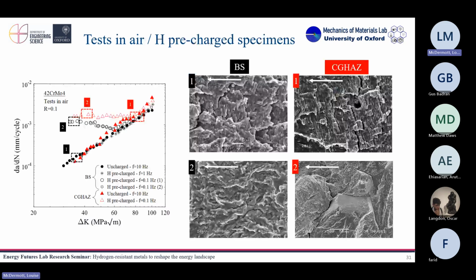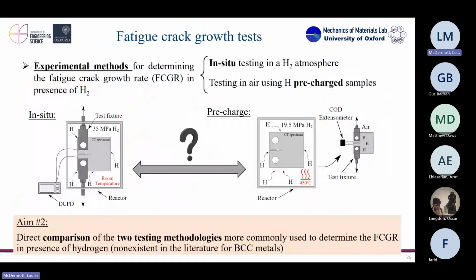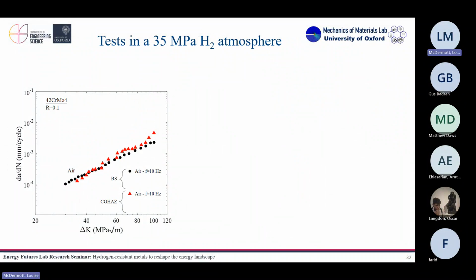And then what we did was the same, but we tested in a hydrogen environment. Okay, remember that the previous was for a sample that I charged with hydrogen and then I test. So now what I said is, okay, I'm going to put my sample in a hydrogen environment, like I did here, and I'm going to test at the same time. And I'm going to apply 35 megapascals of external hydrogen pressure. And what I got was, okay, this is my reference curves, the same as before, no hydrogen, and then boom, what happened here? Completely different, right? But we'll talk about the difference later.